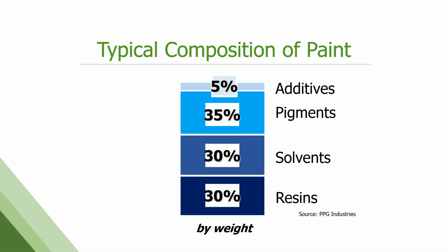So if you look at how these components make up the composition, this is a typical average weight percentage. The resin is a lot of it, again, with the solvents in the liquid form, which are gone by the end. Then the pigments, your pigment to resin or polymer binder is typically pretty equal. So there's a lot of pigments in these systems. And then the additives are very small.